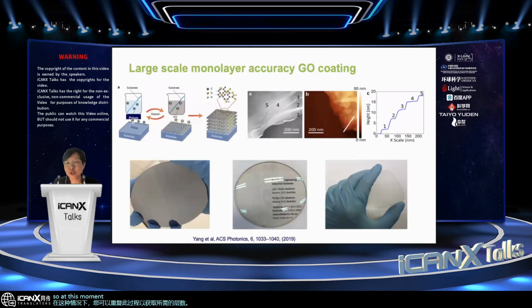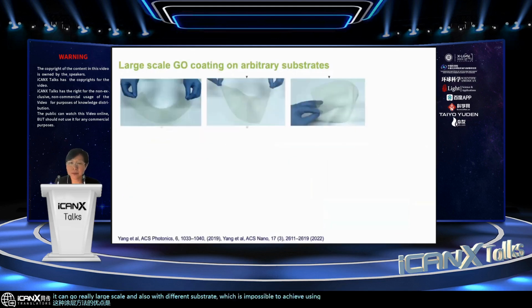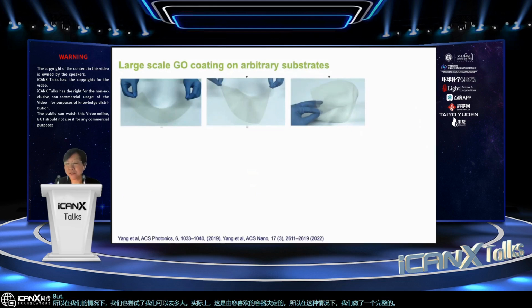So this method can control the layer number quite nicely. In this case, you see 5 layers, and the thickness of each layer is very well controlled. The advantage of this coating method is it can go really large scale and also work with different substrates, which is impossible to achieve using the CVD method. In our case, we also tried how large we can go. Actually, this is decided by your container. In this case, we made an A4 paper size. But as long as your container is large enough and you have enough solution, you're able to coat